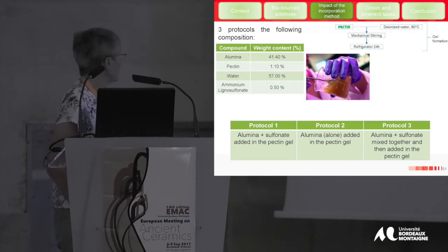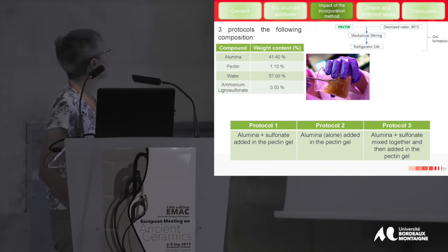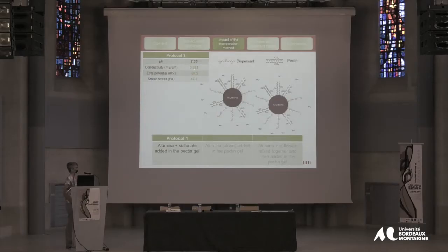So first protocol, again, alumina plus sulfonate added in the pectin gel. What we obtain is a good zeta potential, -50, a small conductivity due to ammonium ion, and a shear stress which is quite adapted to the tape casting process.